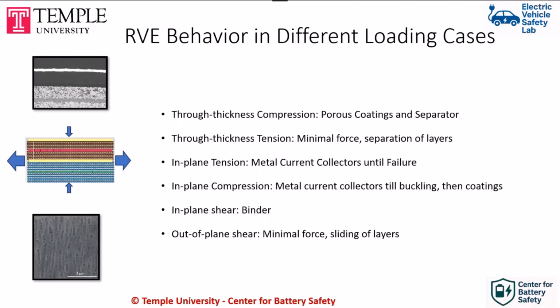So if we understand what is the structure of this representative volume element, then we can understand how we can model that. So if we have through thickness compression, what happens is that the granular material, which is porous, will start to densify, and it starts with a softer property, and usually the metals which are parallel to these layers, they will have not much deformation. Now, if you have through thickness tension, the layers will just separate from each other. So you don't have any strength in the through thickness tension.